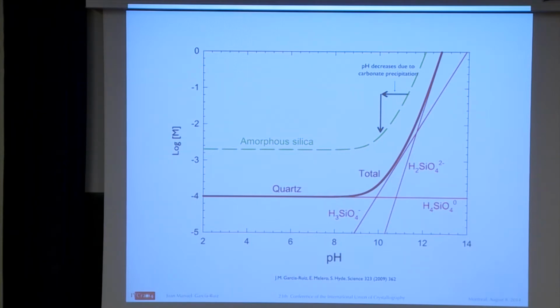But what happens is that the crystal carbonates just start to form, you have a decrease of the pH, and the decrease of the pH provokes the precipitation of silica, right? Because we have here a region in which the first derivative is very high. So the small decrease in pH provokes the precipitation of silica. So the precipitation of silica inhibits the growth of the carbonate-forming crystal, so that they start as a nanocrystal, they cannot grow further, okay?